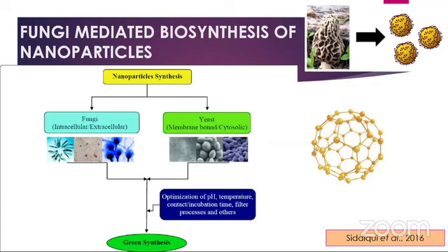When a fungus is exposed to metal salts, like silver nitrate or gold chloride, it first produces enzymes and metabolites to protect itself from unwanted foreign matter. In doing so, the metal ions are reduced to metal nanoparticles without affecting the growth of the fungi. That's why fungi and yeast are these days the promising organisms from which you can isolate nanoparticles. Of course, the exact mechanism of intracellular synthesis of gold and silver nanoparticles is not yet known, but it is certain that in the presence of fungi, they are formed on the surface of the mycelia. That has already been found in research studies.